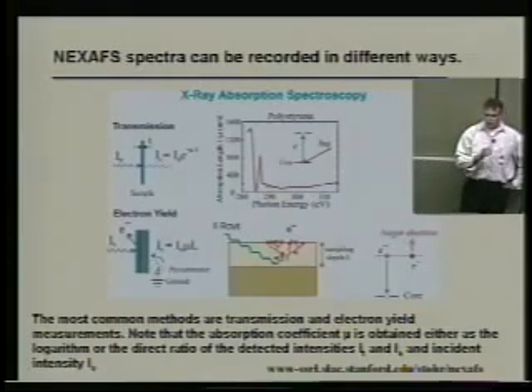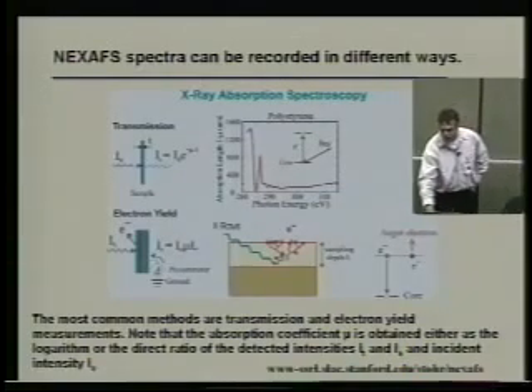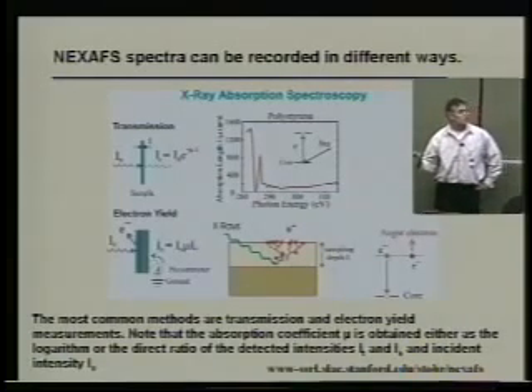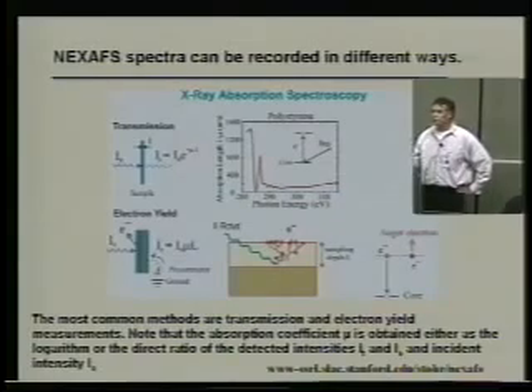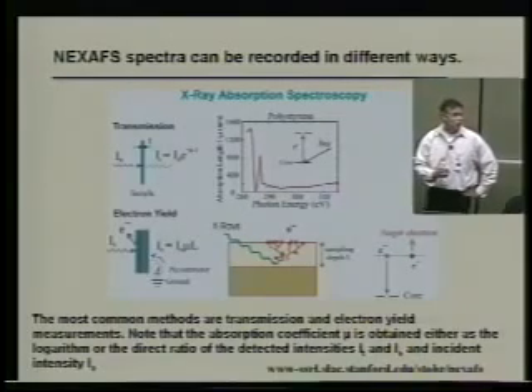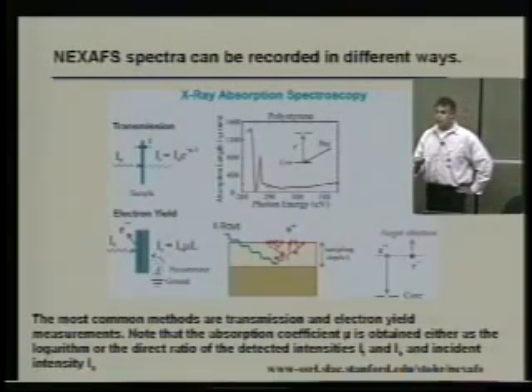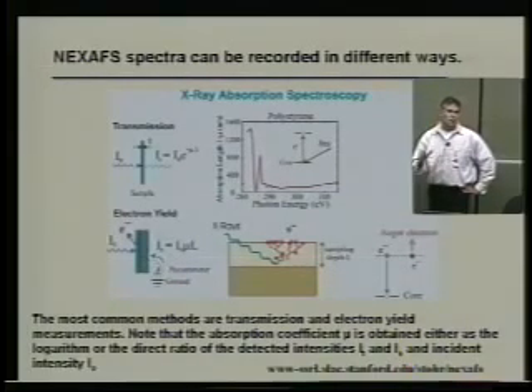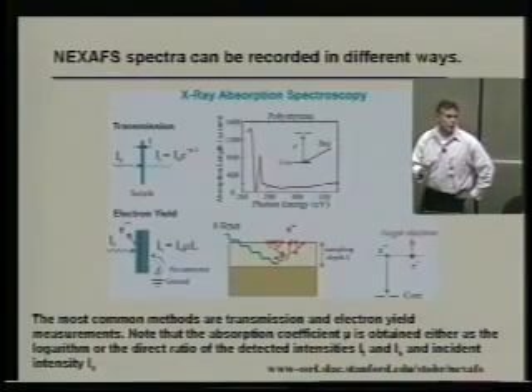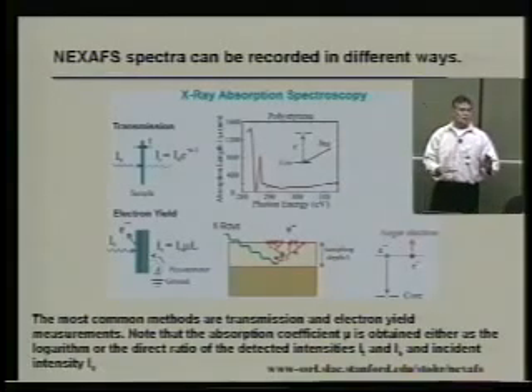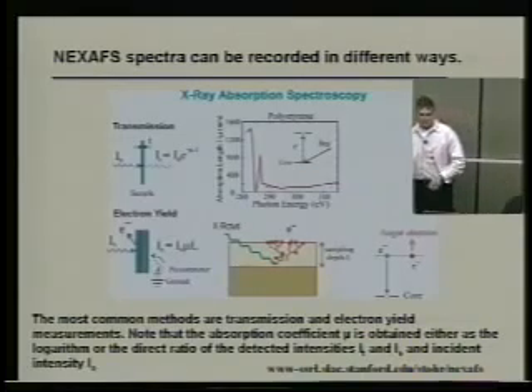Another method that I haven't shown here, but it's very similar to the electron yield, is instead of looking at the Auger electrons, the core hole can decay and you get a fluorescence photon given off. This is fluorescence yield X-ray absorption. By counting the total fluorescence yield photons, you can get, again, a map of the absorption coefficient, and you can map out the X-ray absorption. But here it's bulk sensitive. You're probing down to 1/10 of a micron, in some cases a micron. So by doing different techniques, you can make these techniques surface sensitive or bulk sensitive, and they're element specific.